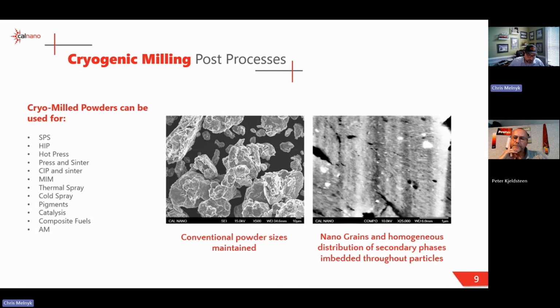So in the early days, the focus was heavily on producing nanograins. And here you can see a typical conventional particle size, 5 to 80 microns. So nothing special on the particle. If you cross-section one of those particles, we have a very nanostructured grain structure. And in this case, ex situ added ceramic particles are uniformly distributed throughout the particle as well. Sometimes those might be formed in situ. Sometimes we might be adding those as dispersoids or adding things in there for various reasons. They could be grain reinforcements, stiffening agents. They could be there for preventing grain growth later on.